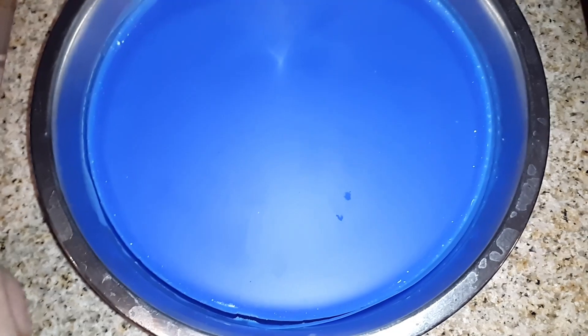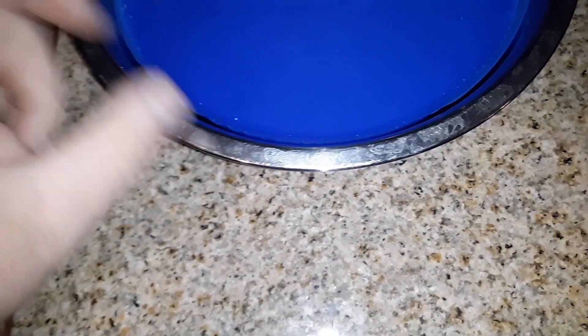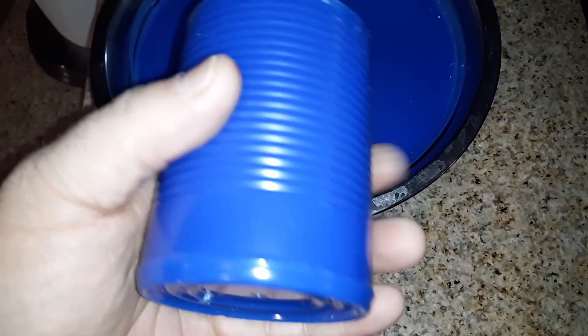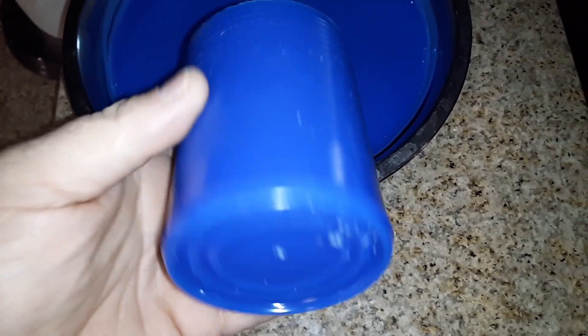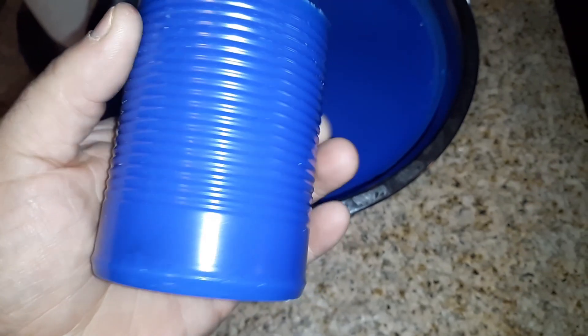So this is after about three hours of cooling — you can see how much it's shrinking already. I'm going to put my plate back over it with the wax paper and just let it continue cooling. It is actually still pretty warm even three hours later, so it takes a good five hours to do this right. Now you can really see it's shrinking — we're about four and a half hours in and there's about a one-eighth inch gap all the way around it now. We'll let this fully cool before we try to remove it. Here is the can — and it comes right out. It shrinks about an eighth of an inch all the way around. The detail of this is amazing — I can definitely see why people sculpt with this as well as cast.